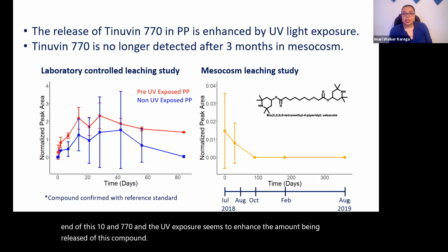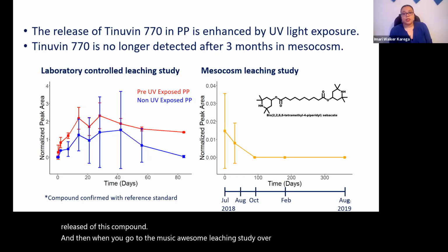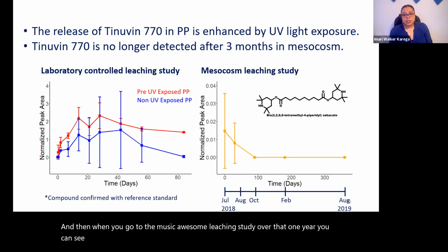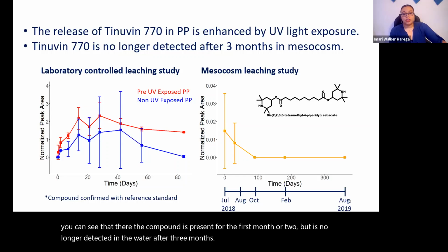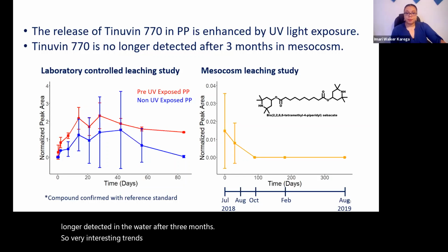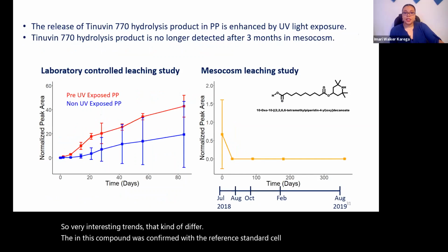The UV exposure seems to enhance the amount released of this compound. In the mesocosm leaching study over one year, the compound is present for the first month or two but is no longer detected in the water after 3 months. Very interesting trends that differ - and this compound was confirmed with the reference standard, so it's definitely in the sample.